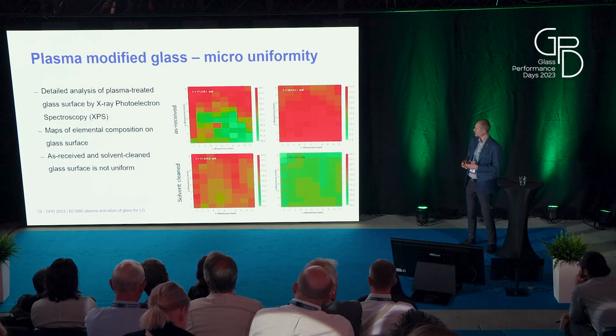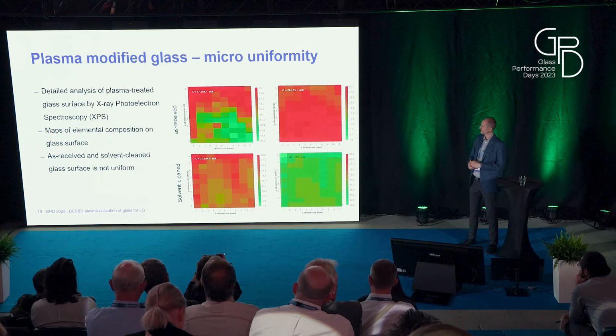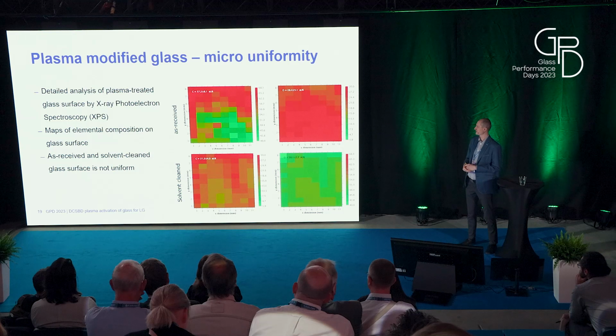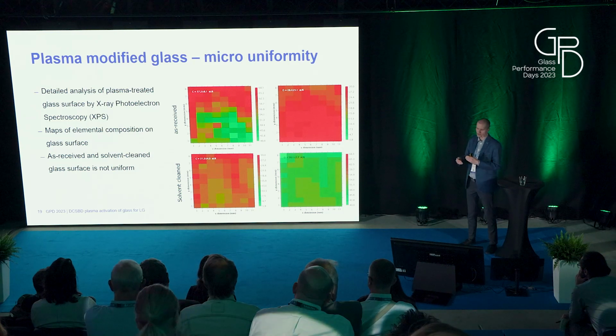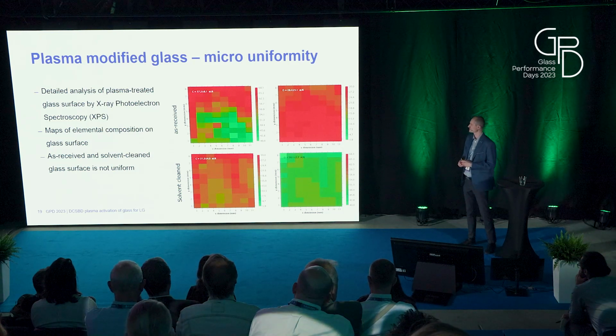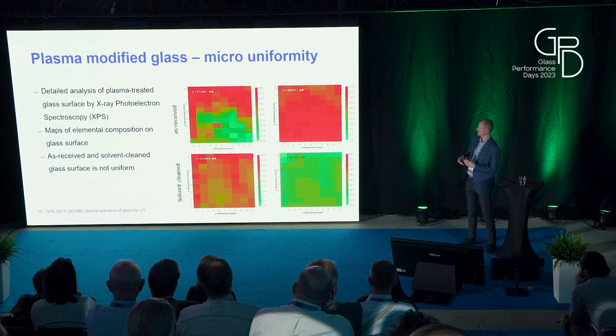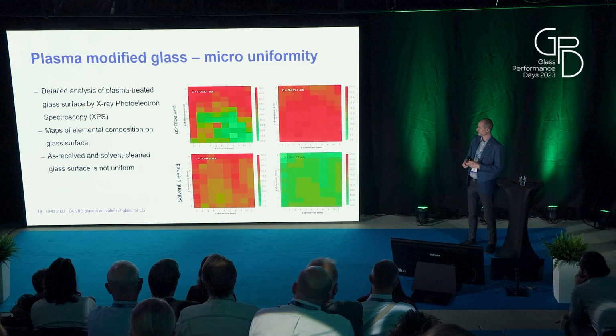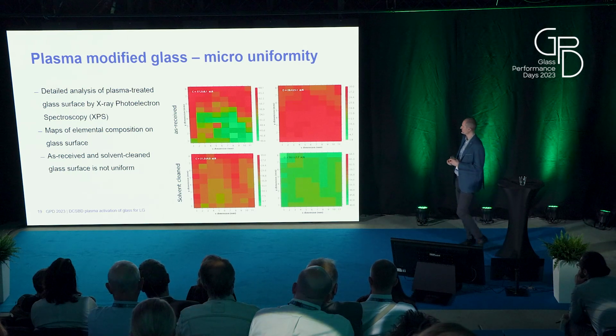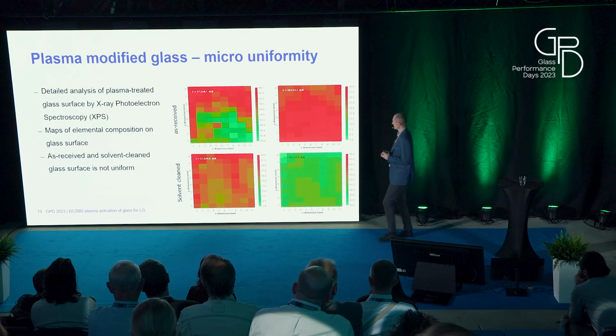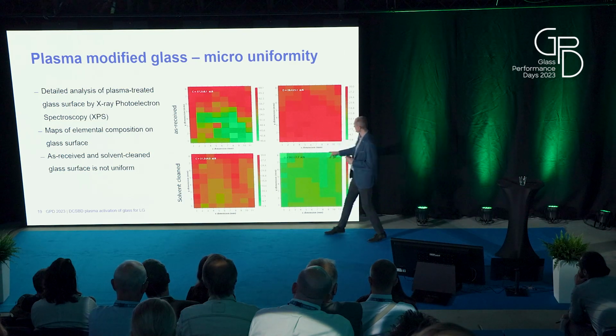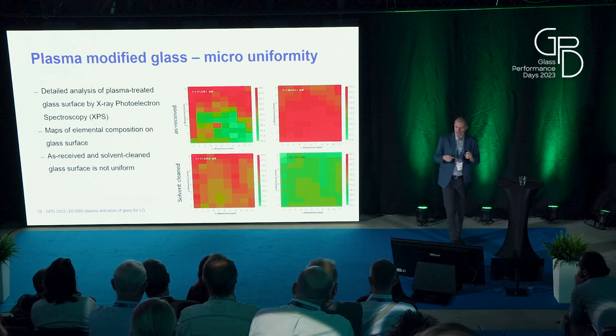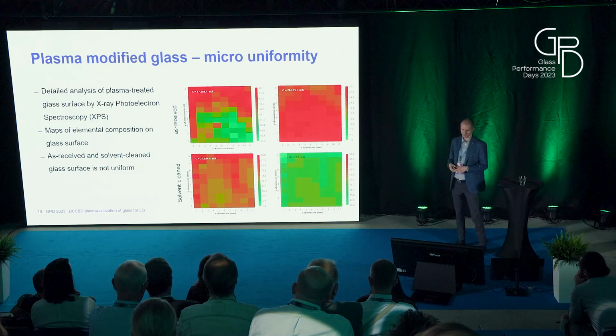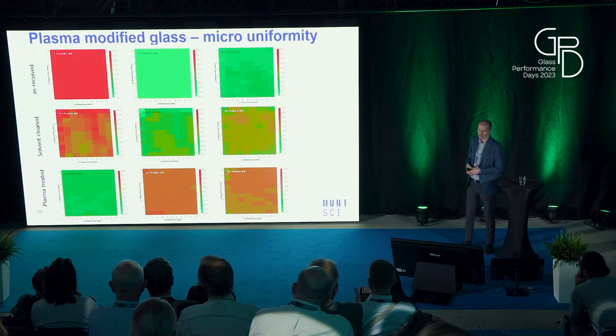And also when you compare it to the wet solvent-cleaned glass surface, there is some improvement in the uniformity, but it's not the best one. Later, in the next slide, I will compare it with the plasma-treated glass surface. What is important, I haven't told you that the dimension of the sample which was analyzed is more than 1 squared centimeter.